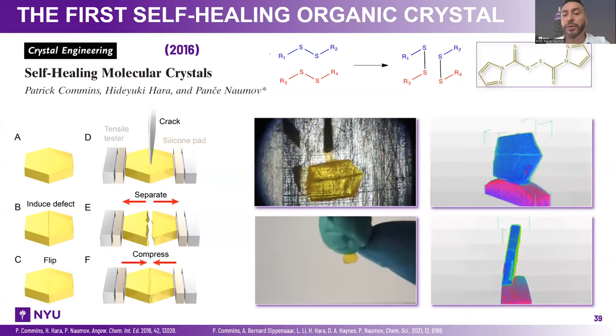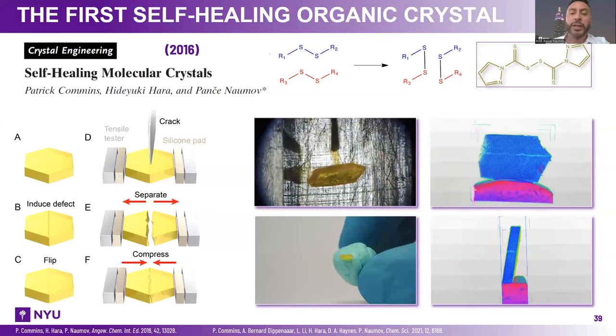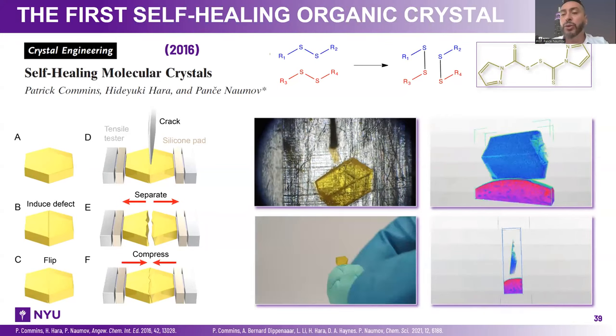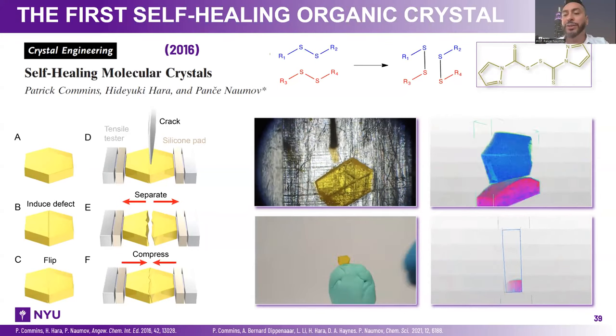So you can play with the crystals, move them around, turn them upside down, and even use computed tomography, as you can see from the right side here, to look inside the crystal to see the difference in the density and actually see the connecting points between the two pieces. So this is our recent development where we use a nano CT or micro CT to look in the interior of the material and see where the connection points are and how efficiently it has self-healed. As I mentioned, this was only 5 to 6% healing. It was encouraging, but very, very low.